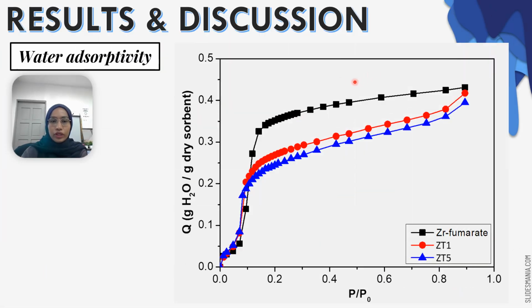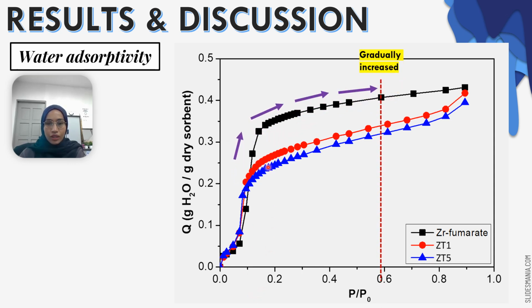Okay, now let's move on to the water adsorptivity of the prepared samples. So this black line here represents the pristine MOF, while the red and blue lines represent the ZT nanohybrids. Firstly, let's take a look at the black line, which is the pristine MOF. As we can see from here, this MOF shows the common water isotherm, similar to those previously reported. There is a gradual increase from the low relative pressure up to a pressure of 0.6. And the maximum water uptake for this pristine MOF is about 40%.